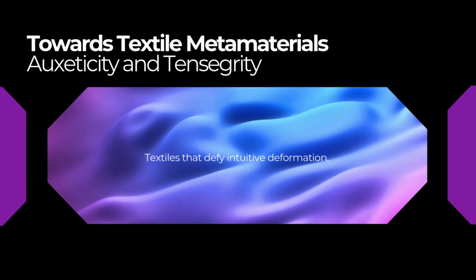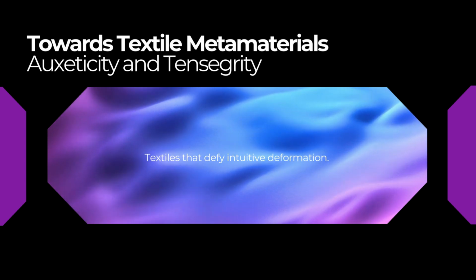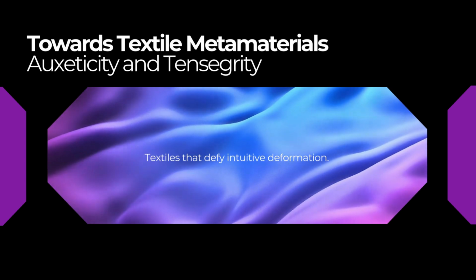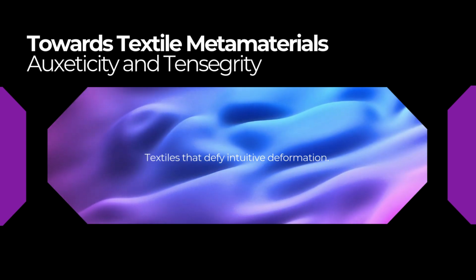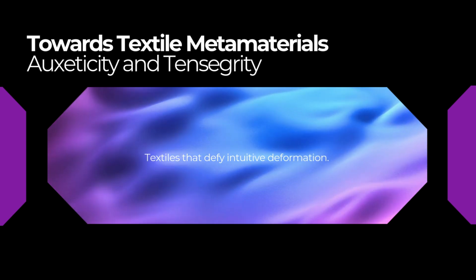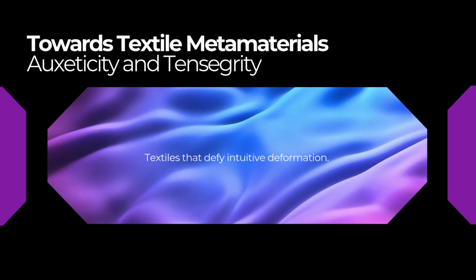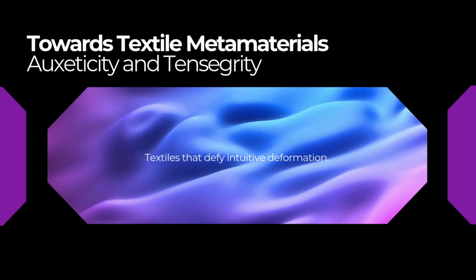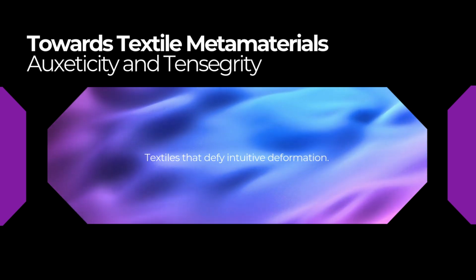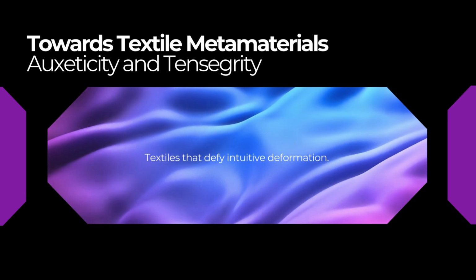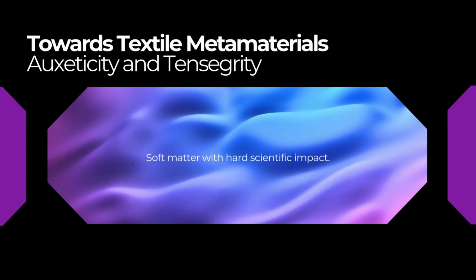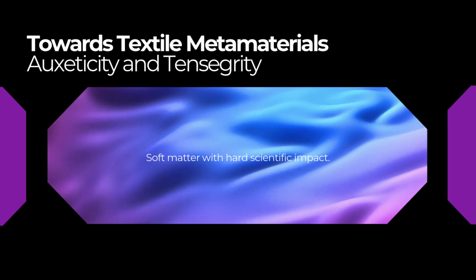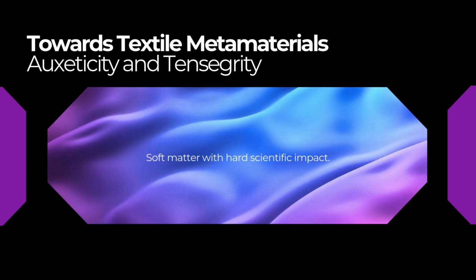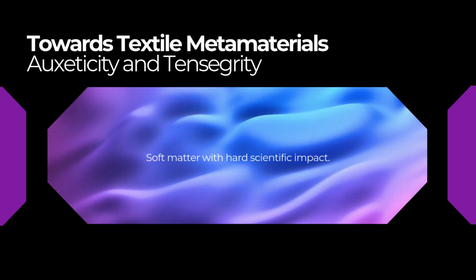And crucially, that locking mechanism translated directly to the property we care about. It substantially enhanced the auxetic response. You got a much bigger thicken for the same amount of pull. The TR samples had significantly larger magnitudes of thickness strain compared to the AR samples, especially at those lower, more practical strain levels. And it got tougher, too. Oh, much stiffer. The TR felts actively resisted being deformed, requiring higher stresses.